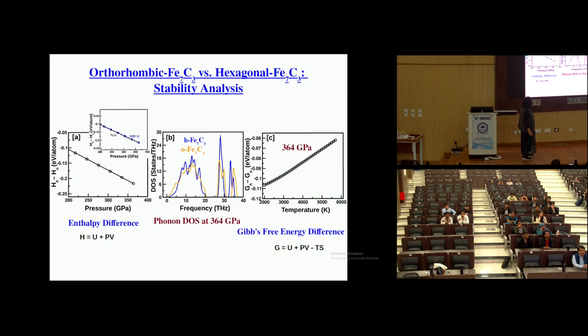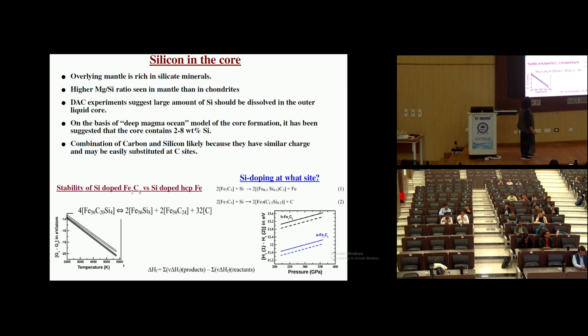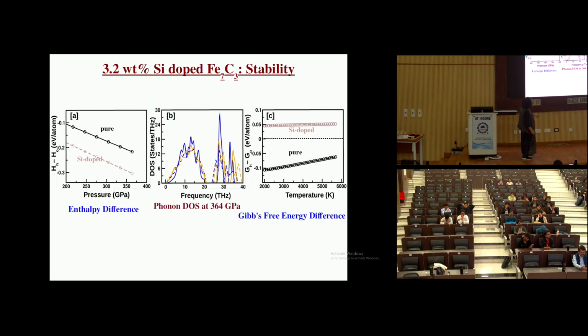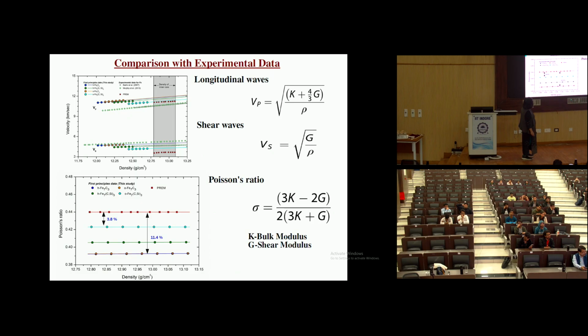What we did is we carried out calculations with two free energies, if you remember from the beginning. One was the Gibbs free energy and another was the Helmholtz free energy. We found that the one that was always favored is the hexagonal phase, but then you have a problem with the density, and then you have to assume something like silicon. On the basis of the deep magma ocean in the core formation, it's suggested that the core also contains some 2 to 8% of silicon. We assumed some silicon, and we found that the silicon replaces the carbon, and with the silicon the orthorhombic phase becomes stabilized.